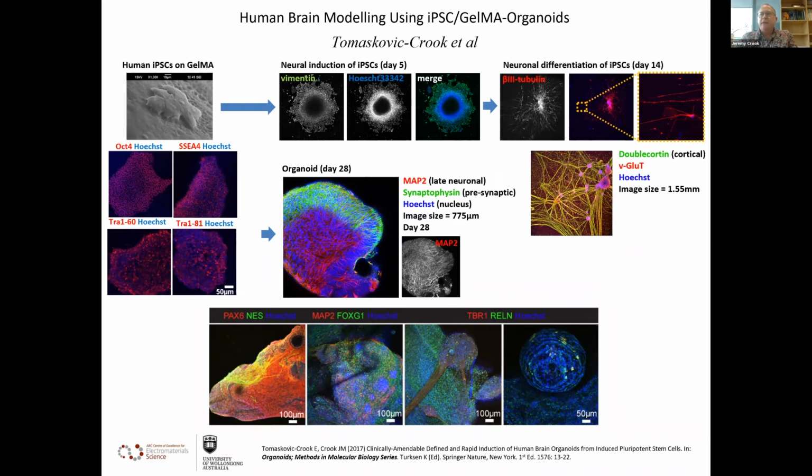It's an inexpensive and easy to handle collagen derivative that comprises both natural cell binding motifs, including RGD, the principal integrin binding domain present within ECM or extracellular matrix, and matrix metalloproteinase sensitive degradation sites for proteolytic breakdown and cell migration, and various amino acid side chain functionalities for covalent modification. Additionally, GelMA remains stable at 37 degrees, which is really important for tissue engineering.